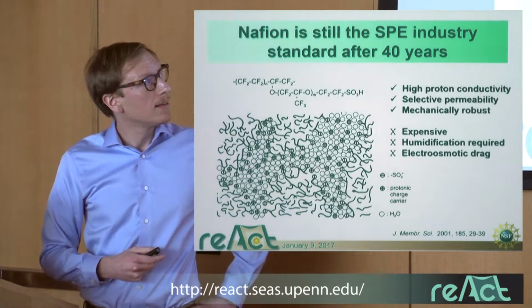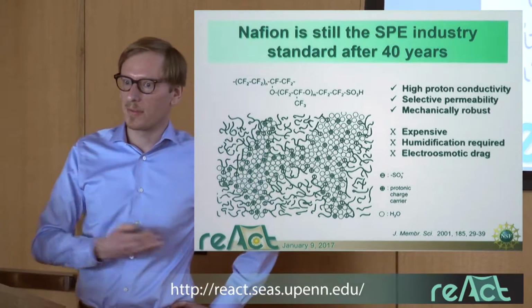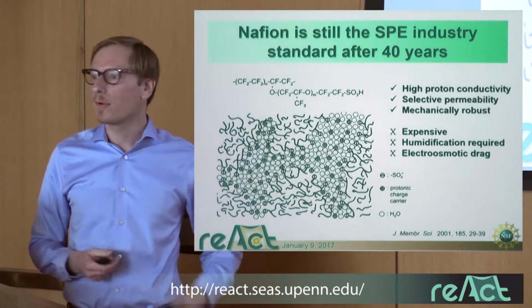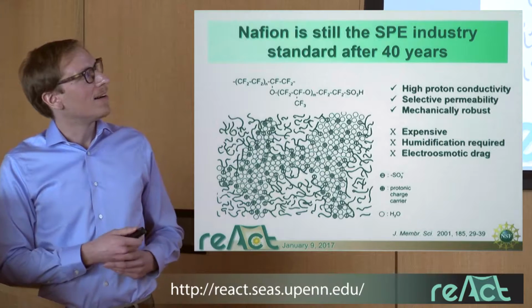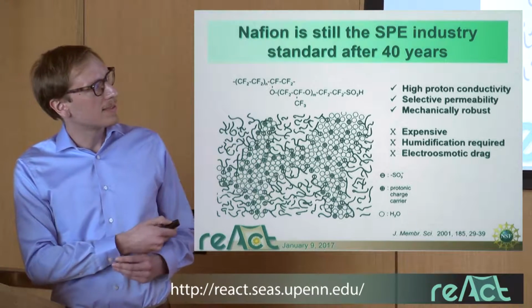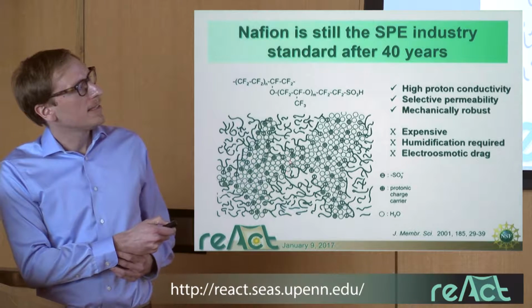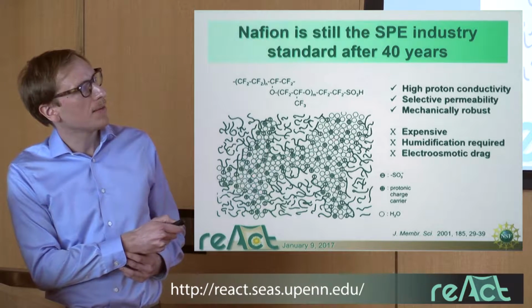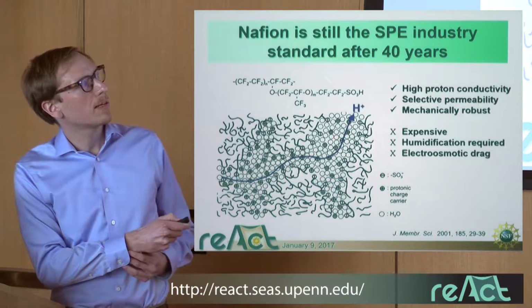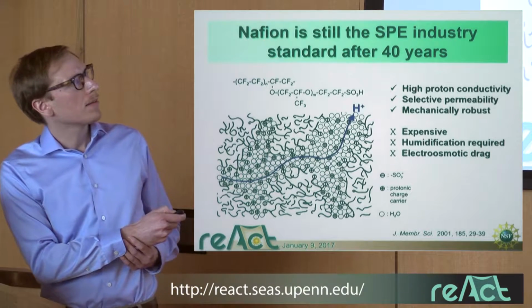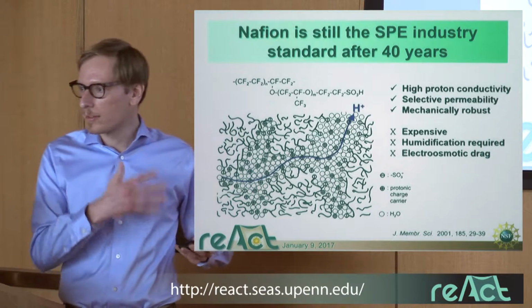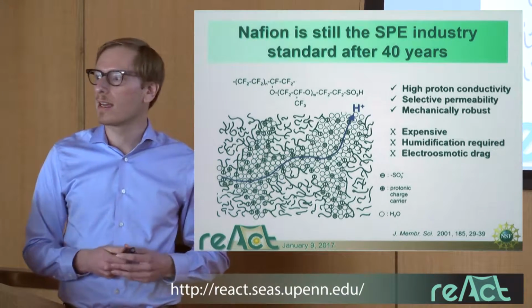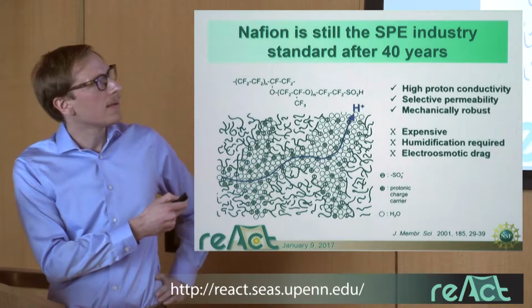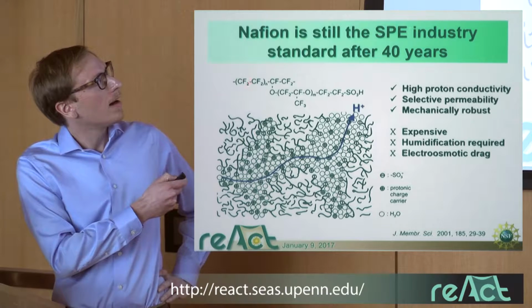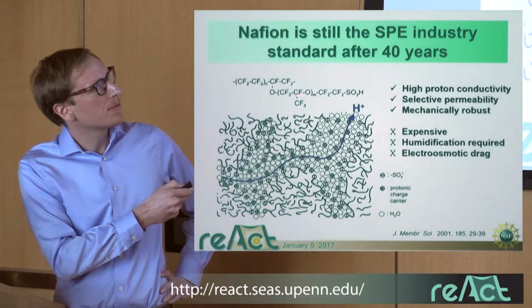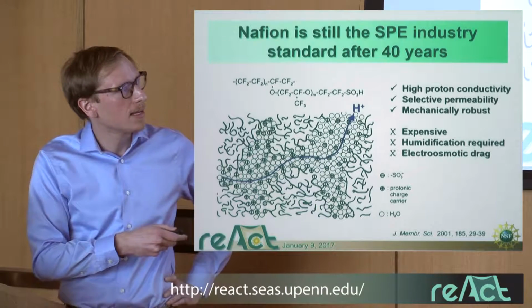And Nafion has been the industry standard for this membrane for around 40 years, which is kind of amazing. But Nafion has this disordered morphology, as you can see here, with these hydrophilic domains which contain water, and those are responsible for transporting the protons through the membrane. Meanwhile, these hydrophobic domains, which contain crystallites, are responsible for the mechanical integrity. This is the chemical structure here. It's a random copolymer with hydrophobic backbone and hydrophilic side chains terminated by sulfonic acid groups.